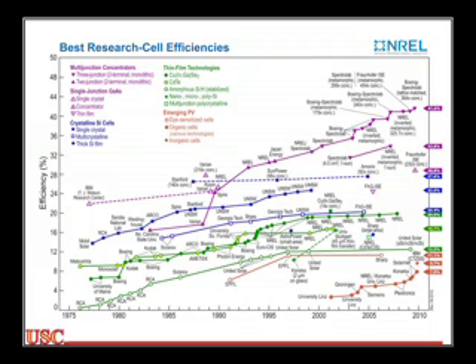There's a recent paper that just came out, this is Giebink, Forrest, and Wasilewski, who went through and did a thermodynamic analysis very close to the one that Shockley and Queisser did in the 60s for organic solar cells, and they expect the maximum for an OPV is somewhere in the neighborhood of 25%. It depends on the order of the system and how much entropy plays into this, but it's expected that we should be able to get into that range if we get all the materials right and optimize the cells well. So there's some hope, right?